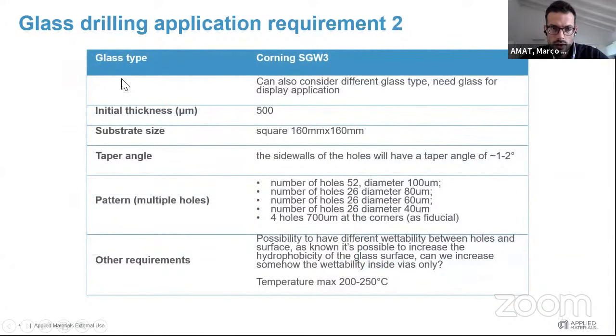Here we also have a specific glass we are targeting. This is the model, a Corning SGW3. Ideally, we are also flexible and open to different kinds of glass, but with similar requirements. Here, the thickness is set at 500 microns, and the substrate size is 16 by 16 centimeters. The requirement on the taper is quite tight because the maximum taper should be between 1 and 2 degrees. And this is a sample.